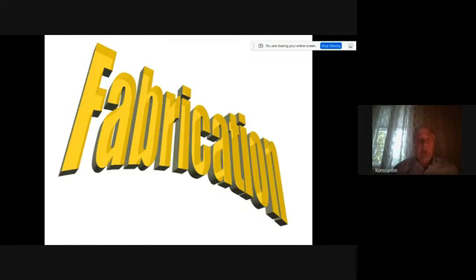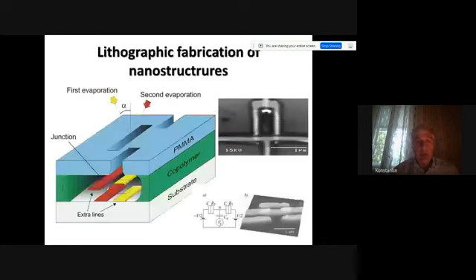So a few words about fabrication of very small nanostructures. All over the world, and our lab is not an exception, very small nanostructures are typically made using electron beam lithography. So we take some insulating substrate, for example, glass, sapphire, silicon, or whatever. We cover it with a special polymer, which is sensitive to optical or E-beam radiation. Then we irradiate particular places, put it in some solvent, and the place where the radiation was applied dissolves more easily, and finally we get such a mask which is shown here.